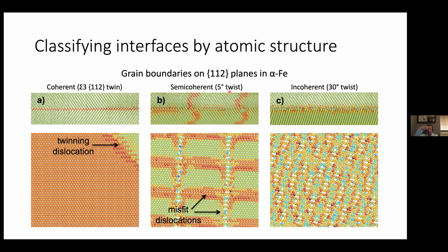If I were to then continue to increase the relative misorientation by increasing the relative twist of those two grains, what happens is that these misfit dislocations get closer and closer together. The coherent patches between them get smaller and smaller. Eventually, the misfit dislocations begin to overlap, and you get something that looks like this on the right. So in this case, I've taken this coherent twin boundary and imposed a 30-degree twist, so a relatively larger twist angle. And as you can see, there's really no evidence of coherency here anymore.